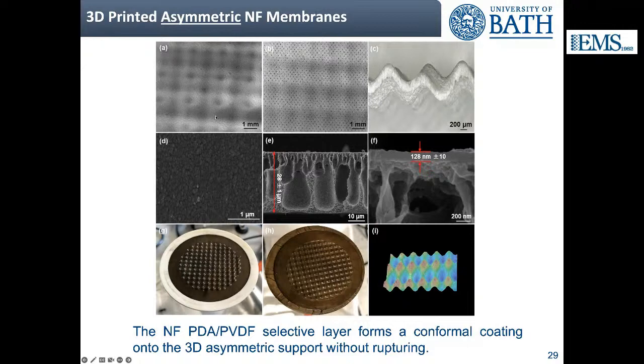Here at the top left, you see a micrograph from the top of the complete membrane, and you can see that the selective layer is clearly following the shape of the underlying support, with peaks and troughs. And here you have a cross section of the membrane. The middle SEM micrographs are of the selective layer, which is about 120 to 130 nanometer thick polydopamine on PVDF. And at the bottom left, you have the final membrane, where again you can clearly see that the nanofiltration selective layer makes a conformal coating on top of the 3D printed support.